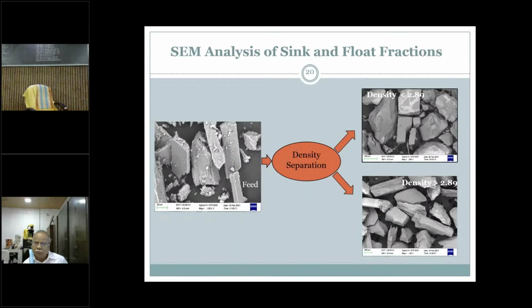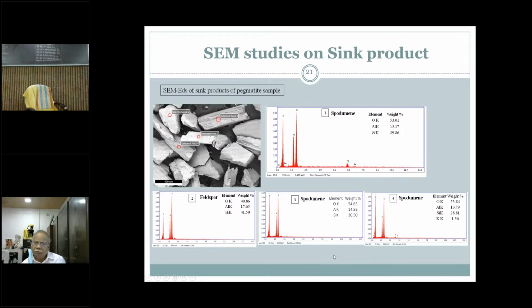Well, these sink and float fractions we subjected again to scanning electron microscopy. You can see beautiful crystals of spodumene have been enriched in the sink fraction. The dumbbell-shaped particles you will find here are the spodumene particles, and the feed had some irregular particles along with the spodumene. You can see the density fraction greater than 2.89 has spodumene, and the density fraction lighter than 2.89 has some silicates.